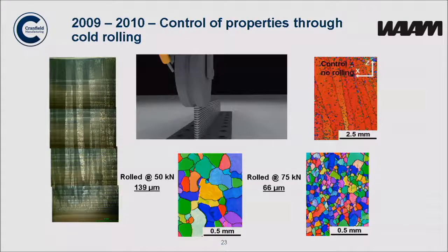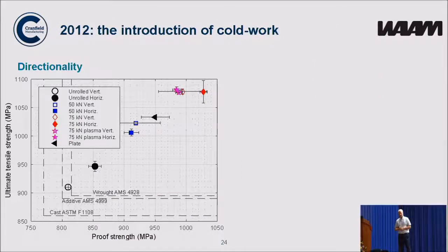When we introduce the rolling process, you can see that we get a very fine equiaxed microstructure. We now have no texture, it's completely isotropic, and we also change the size of the alpha laths so that we get much better properties overall. And you can see this in this diagram here.